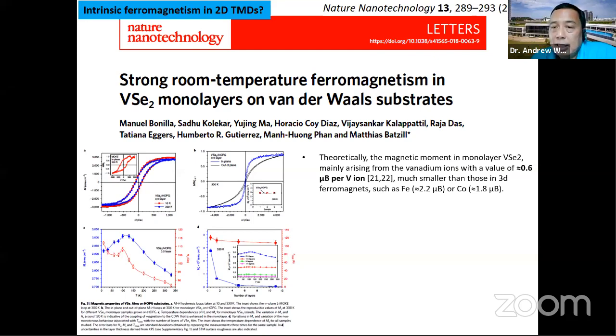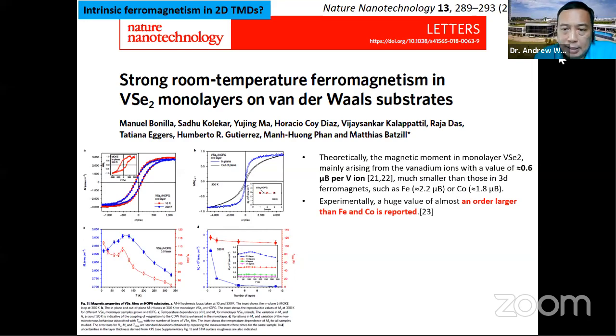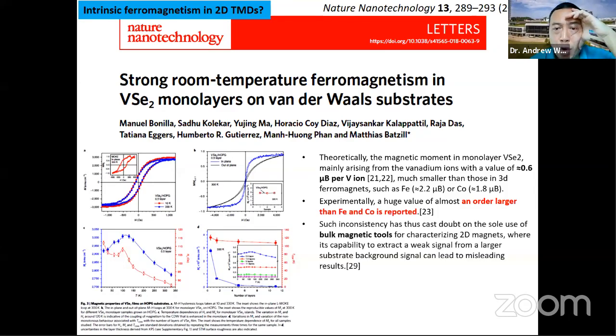Theoretically, it has been predicted that they have a strong magnetic moment, although not as strong as in some of these ferromagnets, like iron and cobalt. But the value they reported was an order of magnitude larger. So that raises certain suspicions. Why was the magnetism so strong?